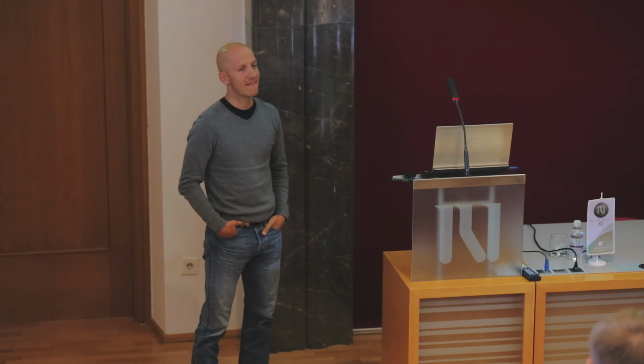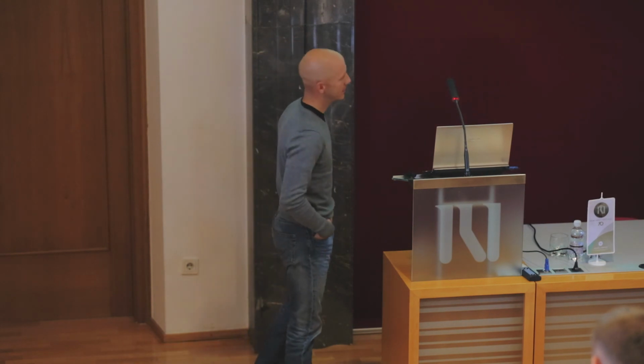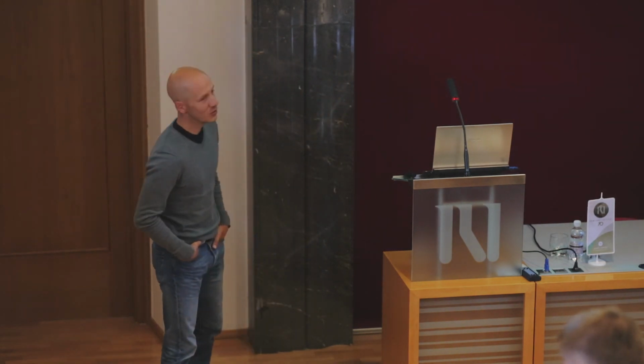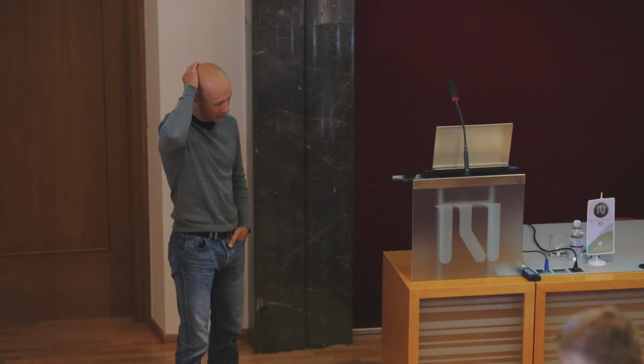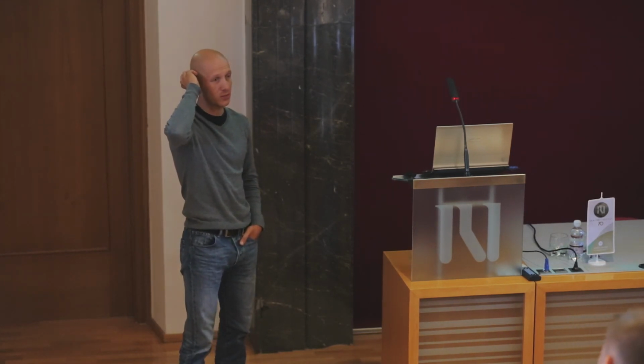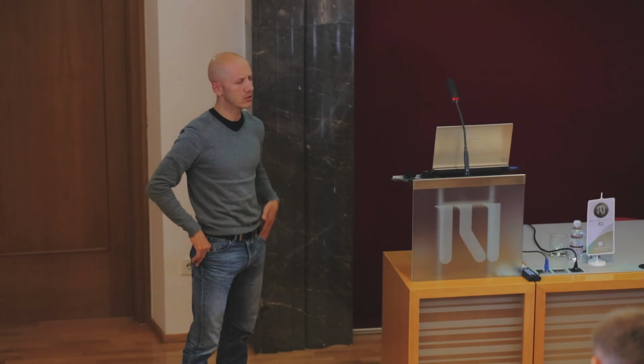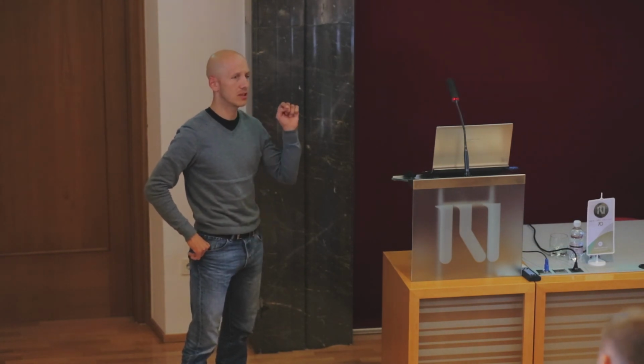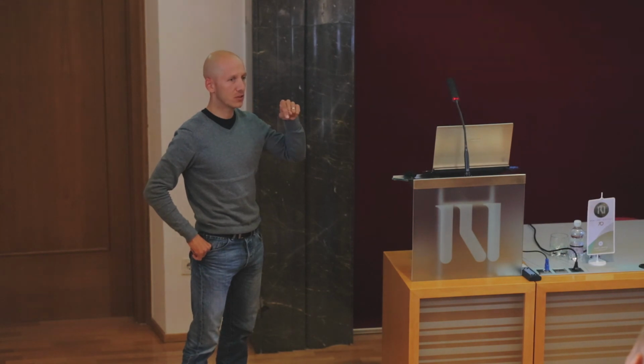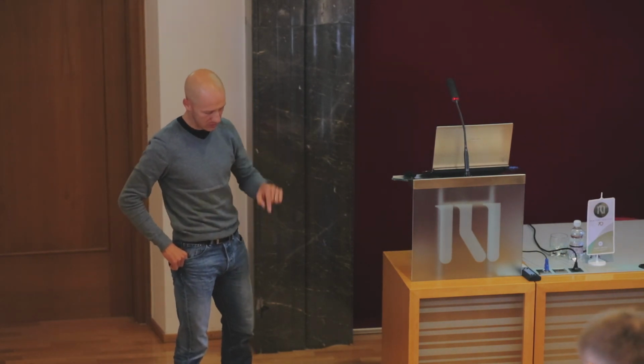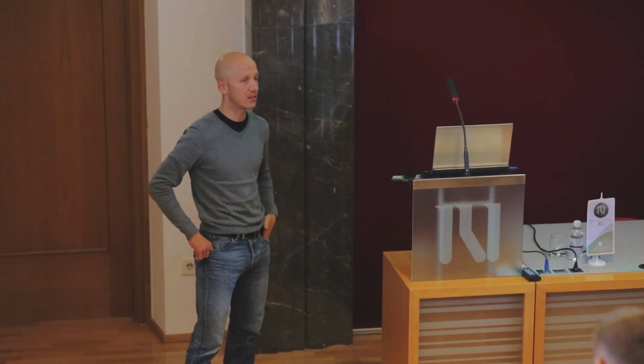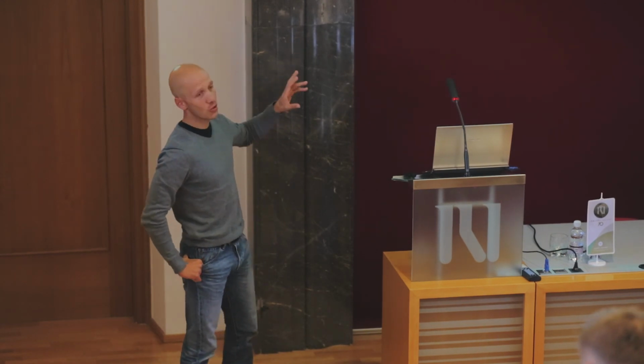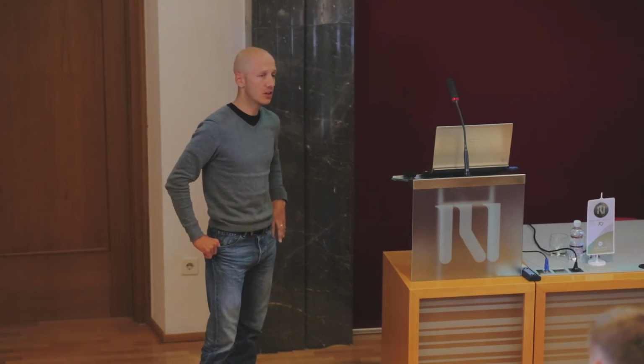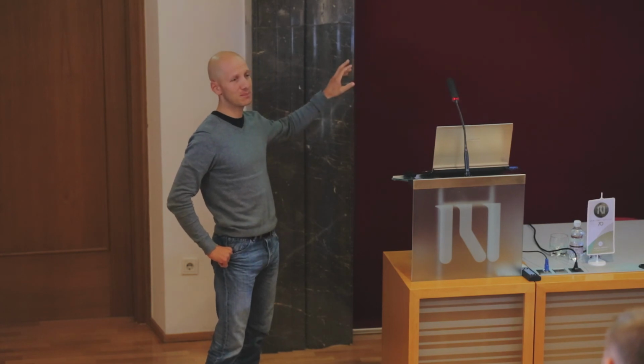So then, if you use graphene or something else, would it work? Or do you think that it has to be selective towards covering? I think we just hit the sweet spot with these molecules. Graphene is also impermeable, although there are a couple of papers showing that there is proton permeation through the graphene lattice. However, I did not want to show our latest results because now we work a lot with graphene, so I don't want another patent to get denied.